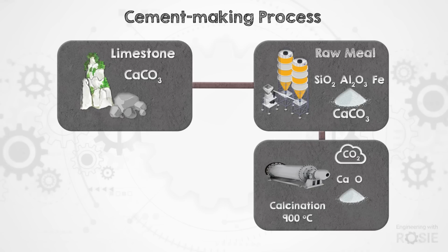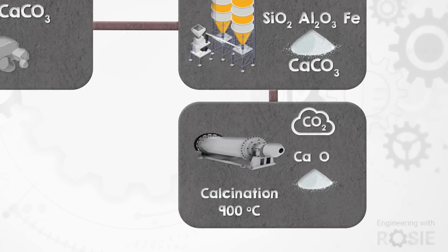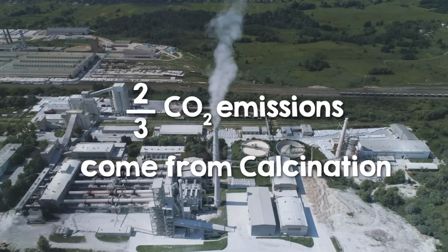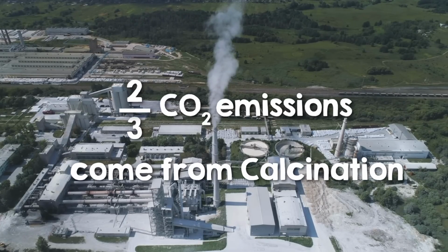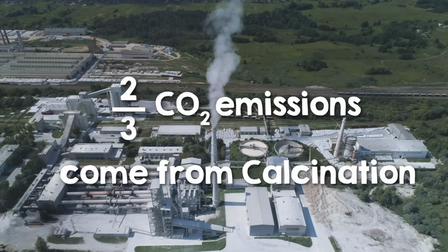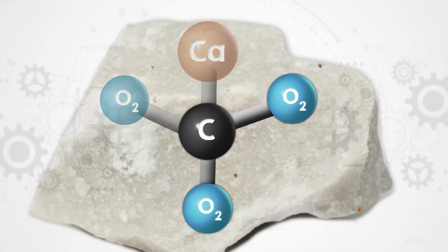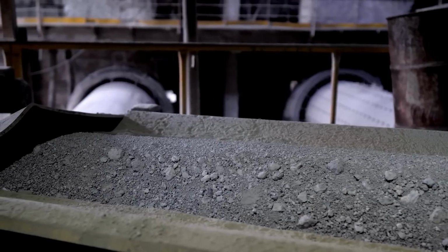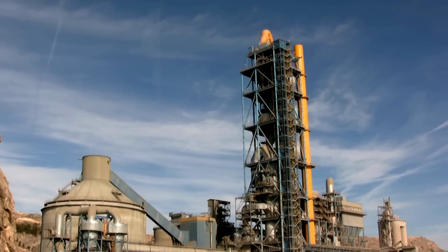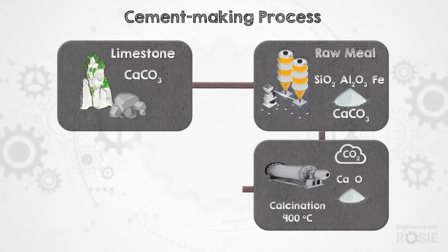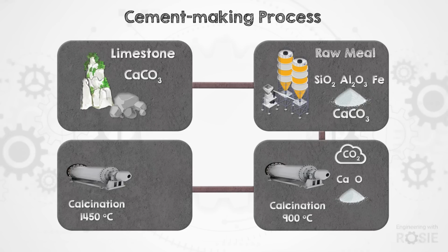The CO2 is emitted into the atmosphere, and this part alone is responsible for about 2/3 of the emissions from cement production. The CO2 that's emitted here is a non-negotiable part of that reaction because limestone is 44% CO2 by weight, which is trapped in the rock, and it's released when making lime. If you want to turn limestone into lime, you simply cannot avoid releasing CO2. As the temperature increases to around 1450 degrees, calcination continues, and the calcium oxide reacts with the silica, alumina, and iron to form compounds known as clinker minerals.